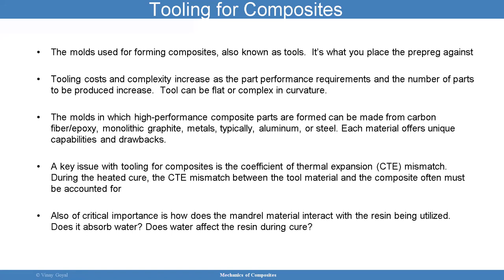Also of critical importance is how the material interacts with the resin being utilized. If you use a material that could have a negative and adverse reaction with the composite, that could be an issue. Does the tooling material produce water? Because then the water affects the resin. So you have to keep in mind all these things as you're working it through.